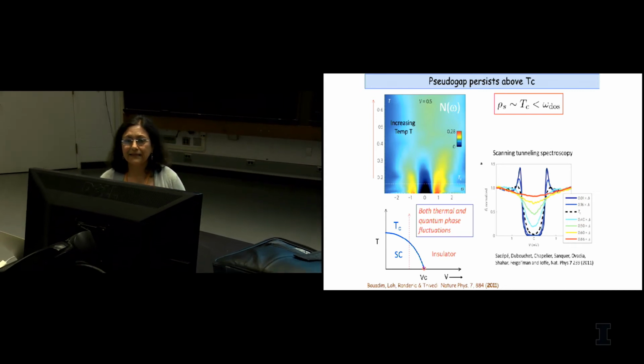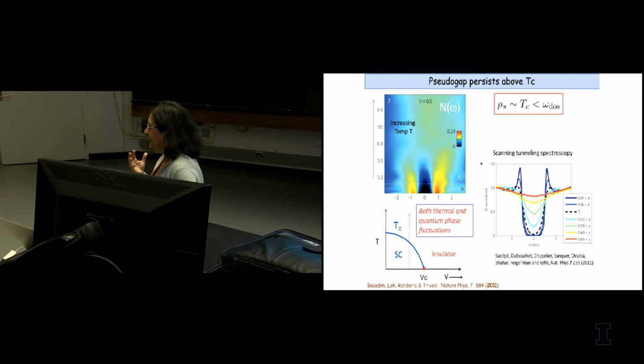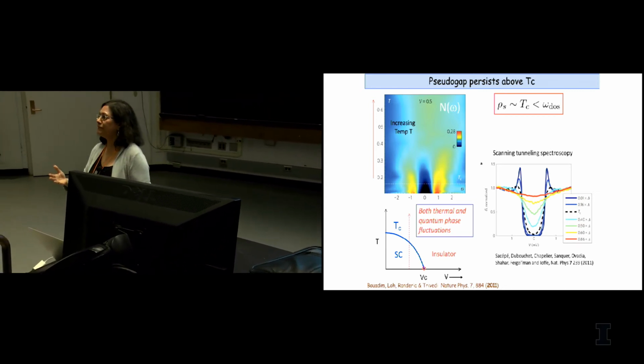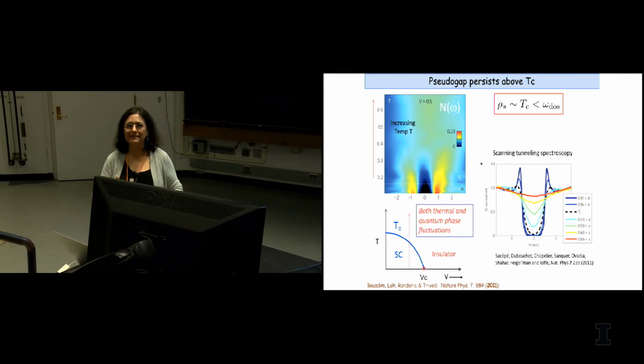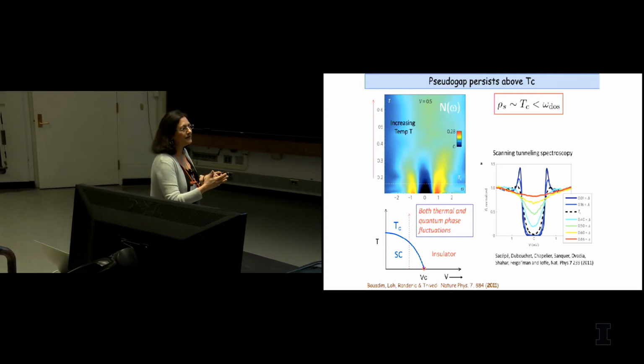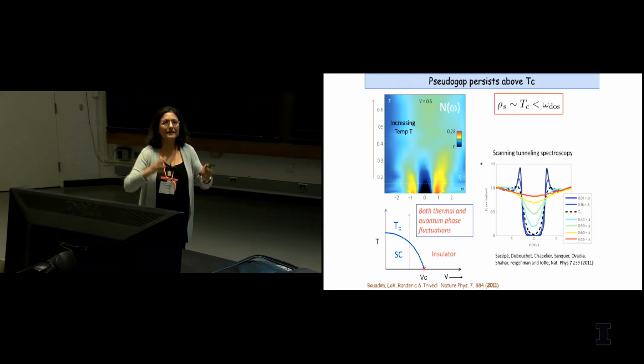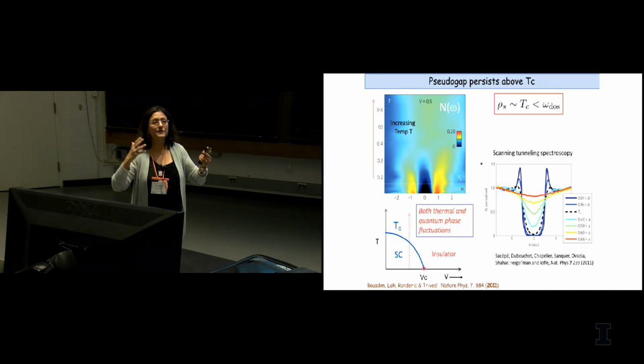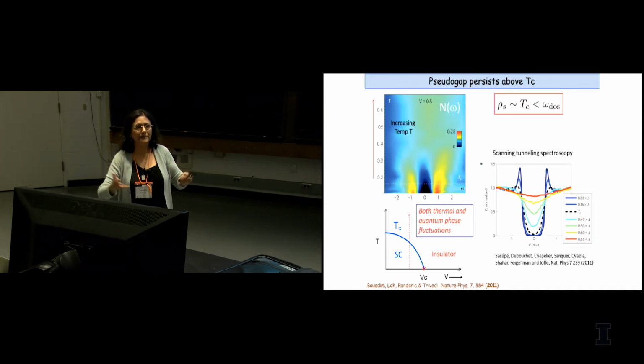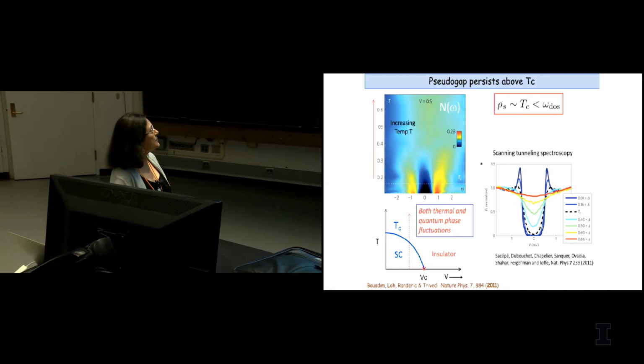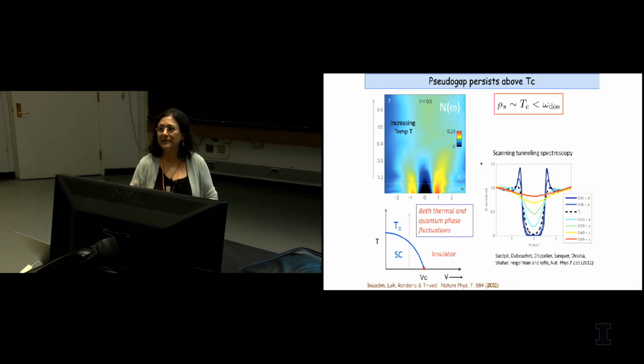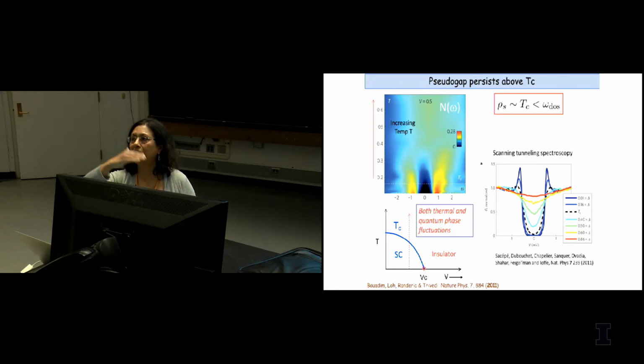So that's a pseudo gap opening in this case due to disorder effects. This is not to say that this is the explanation of the pseudo gap in the cuprates. It's just that different systems can have different reasons for opening up such a pseudo gap. But nevertheless, we are seeing the breakdown of the BCS paradigm, within which at Tc you would have recovered the normal state.